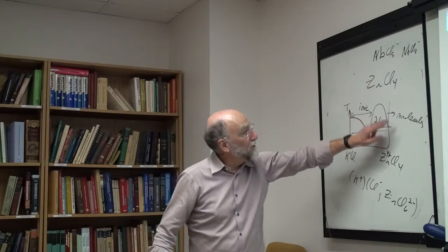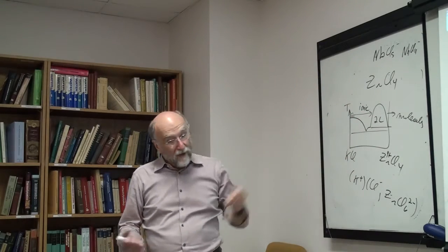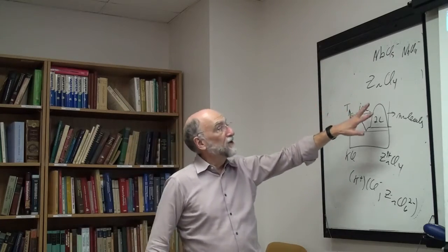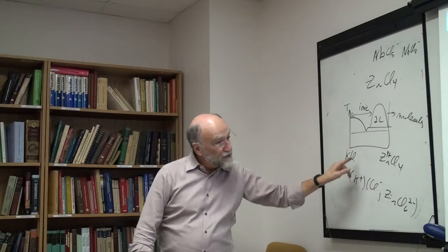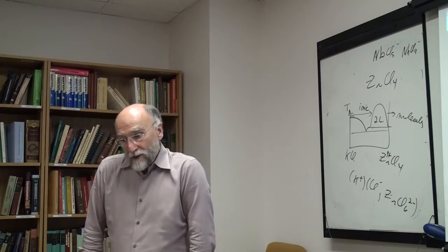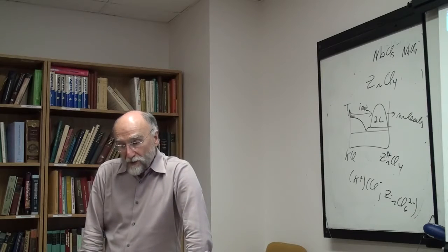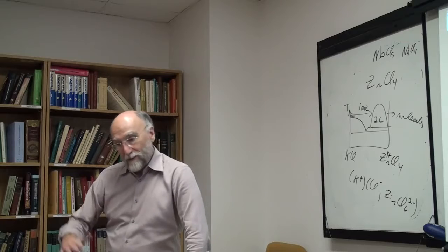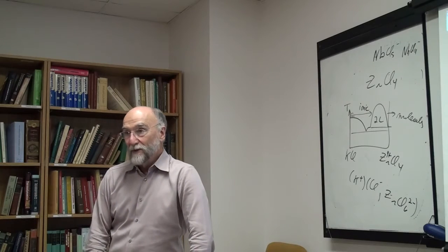So things like niobium, zirconium, aluminum are strongly complex. The aluminum chloride is less strongly complex than the aluminum fluoride system, and so on, because the fluorine is small. Okay, so as the ionic size goes up, complexing energy goes down. As the ionic charge goes up, complexing tends to go up.